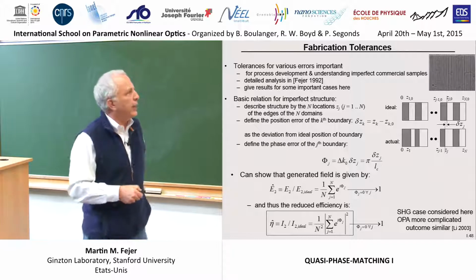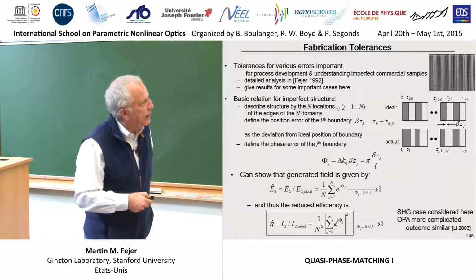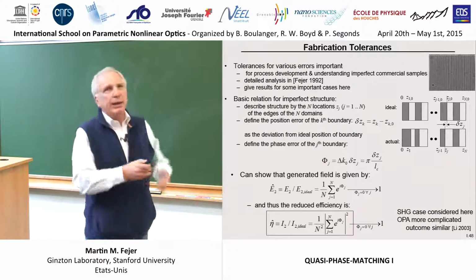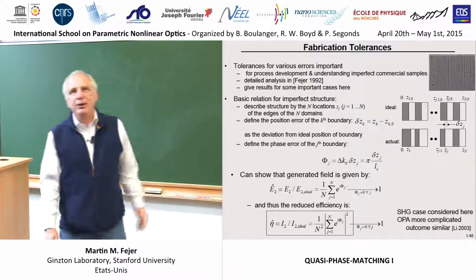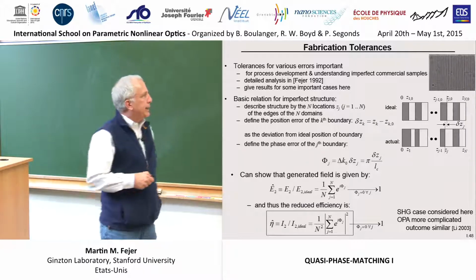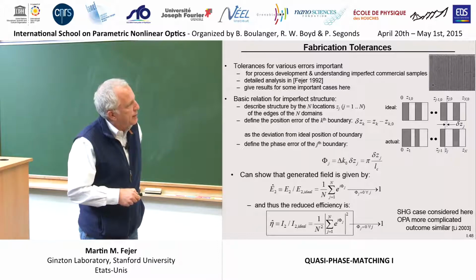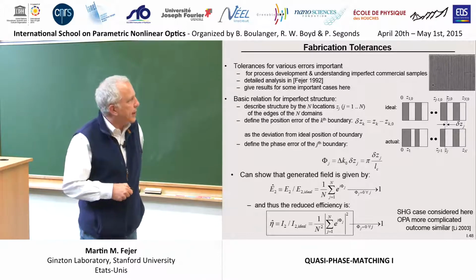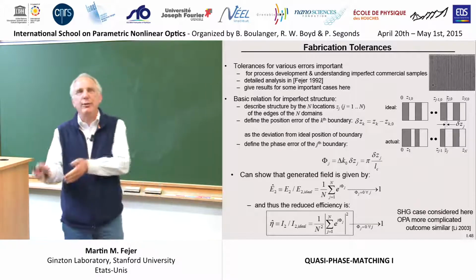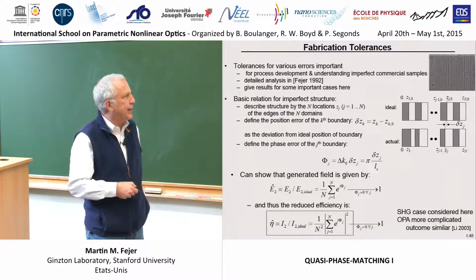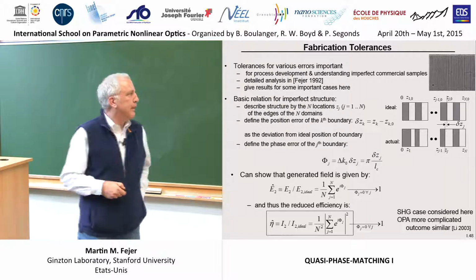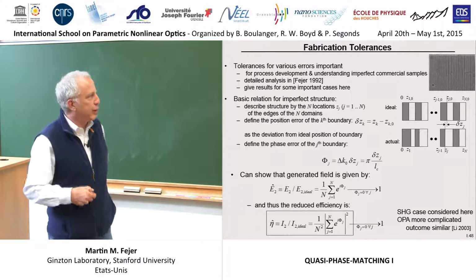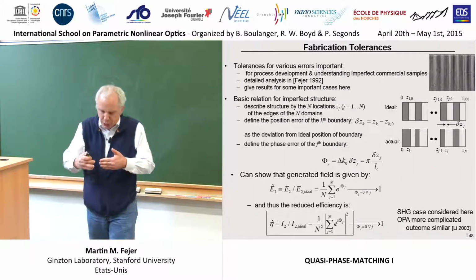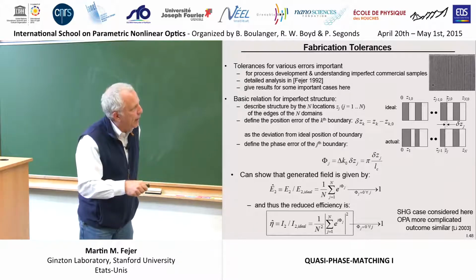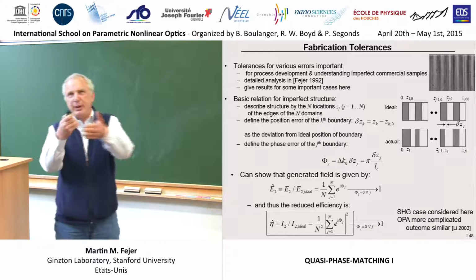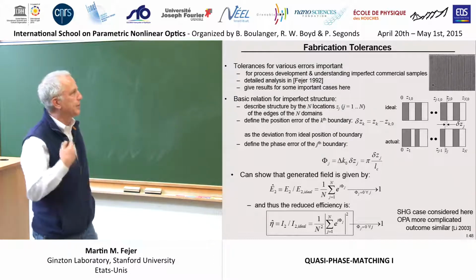And so we can describe our structure by the statistics of the errors, the nature of the errors of these 10,000 domain edges, or however many your sample has got. So it's useful not to speak of the absolute thickness position error delta z, but rather what is the extra phase shift associated with that error, and that just goes like delta k times that position error, or equivalently pi times the position error compared to the coherence length. That tells you what fraction of a pi your phases of your waves are wrong when they hit that interface instead of being perfect as they would if it was where it belonged.